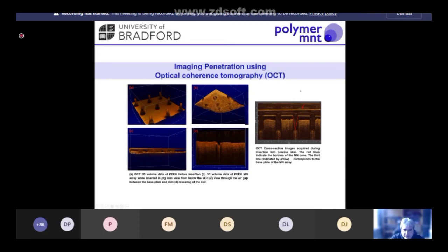And finally, once we've done the penetration tests, we can use techniques such as optical coherence tomography to image the microneedle device within the skin. We can do this not quite real time, but pretty quickly. So we can look at the deformation with time, and correlate needle penetration behavior within the skin at given times during the application. On the right hand side here, you can see the needle structure, the needle form, as it progresses in the skin. So we can measure the depth of penetration. We can see how it's gone in there. And with dissolvable systems, you can see how they decay over time too. So it's quite a useful technique for monitoring our penetration performance.